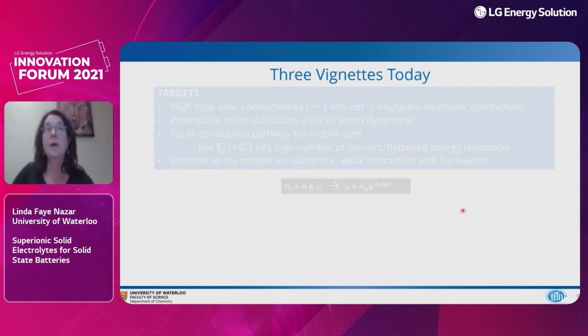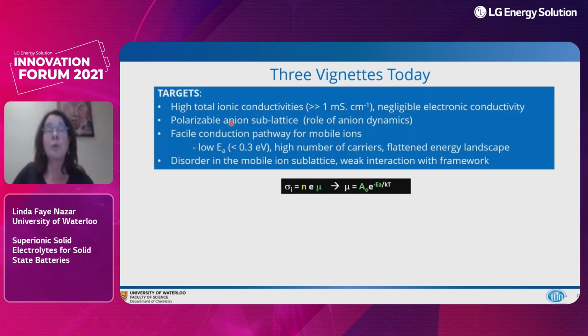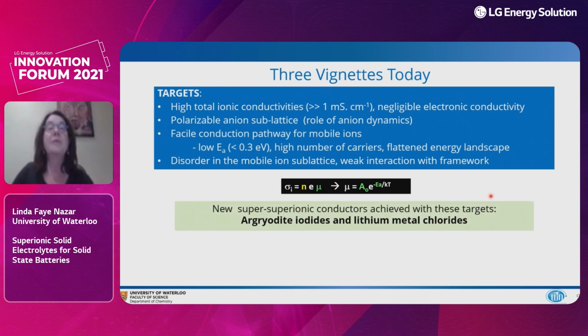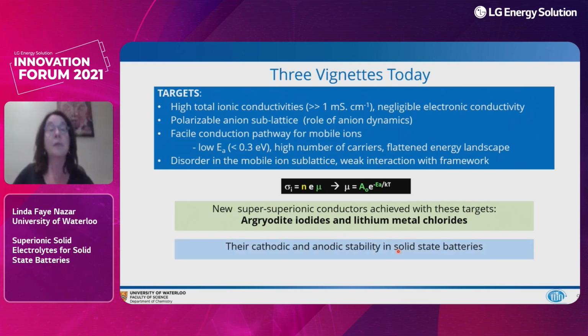So in today's talk, I'll be talking about the role of anion dynamics in achieving higher ionic conductivities, achieving fast conduction pathways for mobile ions, which have activation energies lower than 0.3 electron volts. And we do this with a strategy of effectively tuning the number of carriers and/or flattening the energy landscape. Inherent to this is achieving disorder in the mobile ion sublattice by weakening its interaction with the framework. So we've achieved, as I mentioned, some new superionic conductors with these targets, and I'll be talking about those and their cathodic and anodic stability in solid state batteries.